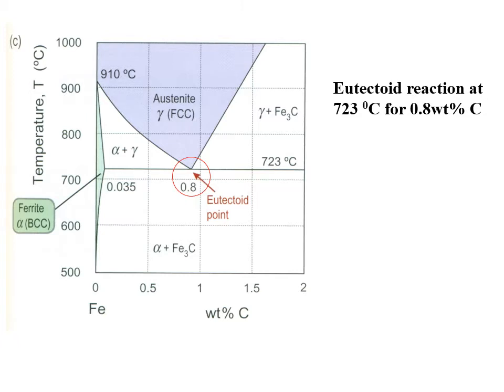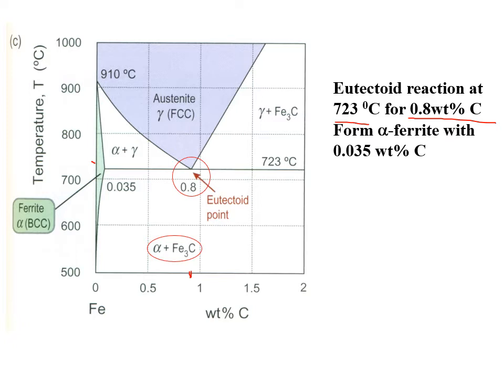Looking again at our percent weight of carbon versus temperature graph, zoomed in now from 0 to 2, what we want to look at is the eutectoid reaction, and we can see this occurs at 723 degrees Celsius on our y-axis, at 0.8 percent weight of carbon, which we come down to on our x-axis right here. Remember, if we take a look over here, we can see ferrite forms with 0.035 percent weight of carbon. And cementite forms, if we recall from a couple slides ago from the larger graph that went out to 7, with 6.6% weight of carbon.